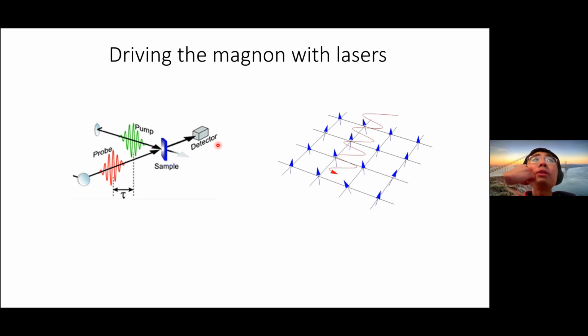The rough idea, the experimental setup in this situation, is the so-called pump-probe experiment. The idea is that first you send in some pulse, say a periodic pulse, into the system with a certain frequency, and this pulse would generally excite the system or drive the quantum magnet by pumping energy into it. Then later, after a certain time after this pump, you can send in another pulse to probe the system through the detector. This gives us a way to drive the system out of equilibrium.